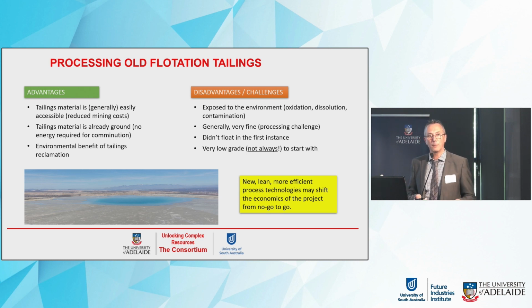And the final thing is, normally it's very low-grade material, but as I said, not always, because the low efficiency in the past made material which was a relative high grade ended up into the tailings. So sometimes you have very nice discoveries. What I thought it was a tailing deposit, it's 2% grade zinc, 3%, so that's a good deposit to me. So there is pros and cons.